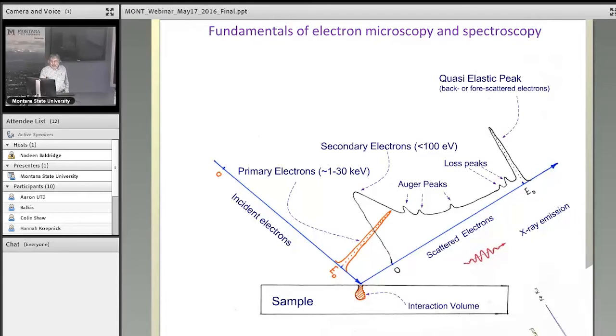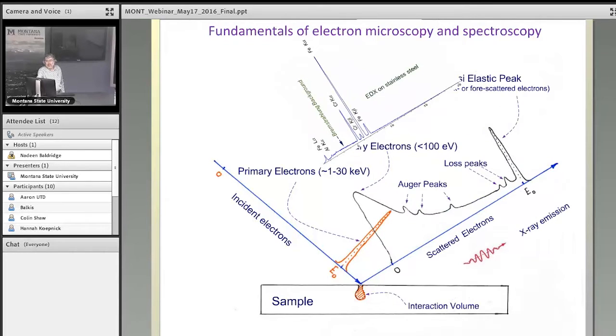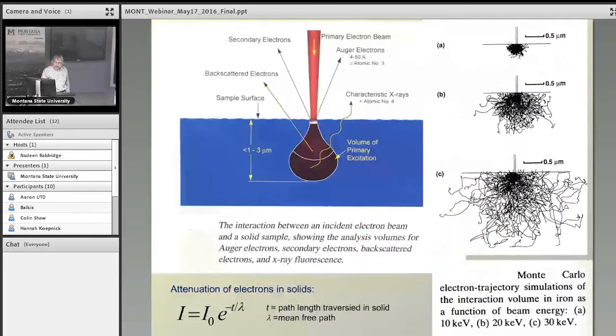So you take X-ray data, you see something like that. I'll get back to that in the next slide, but let me just talk a little bit about the bulk versus surface analysis. This is the incoming beam entering your material right here, about a couple nanometers at best. It's a very tiny spot. When it goes into the solid, let's assume it's a 20 keV beam, it's ricocheting, going back and forth, scattering and scattering, and every time it scatters, it produces either an X-ray or an electron. If the electron is produced near the surface, it will be an Auger electron or the secondary electron. We use them either for imaging or for elemental analysis. So this is the interaction volume, excitation volume essentially.